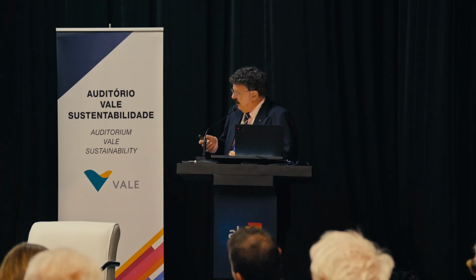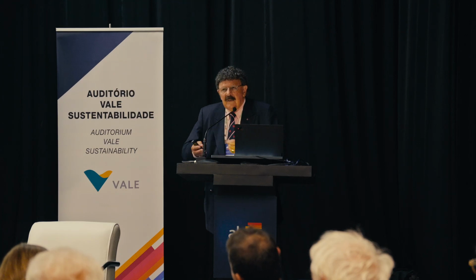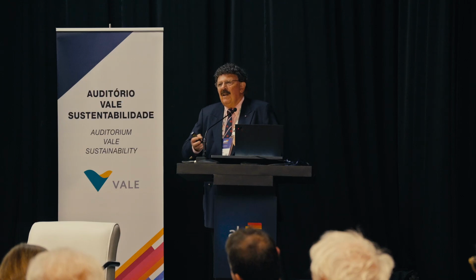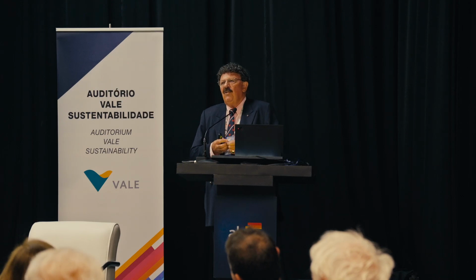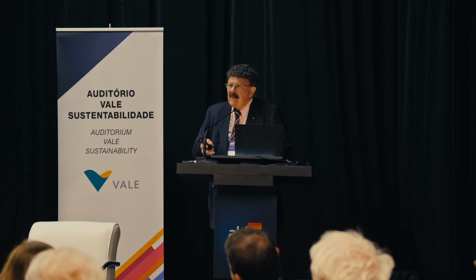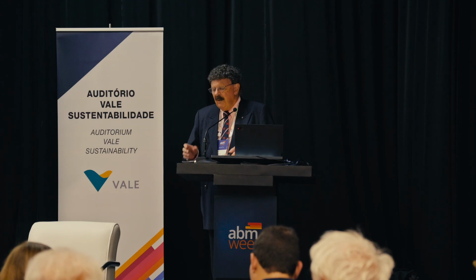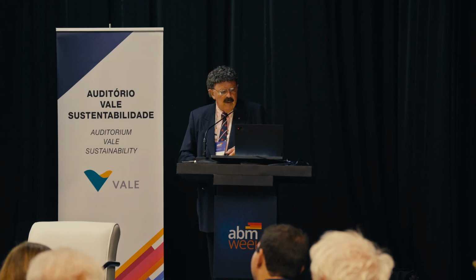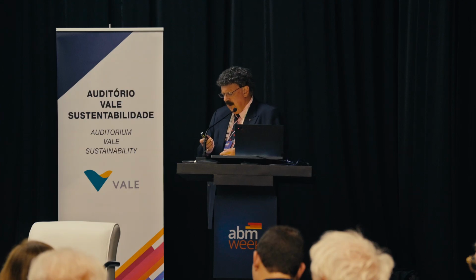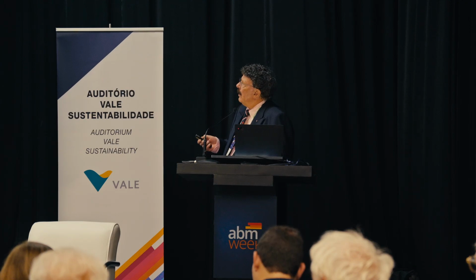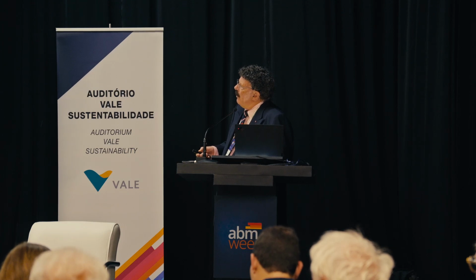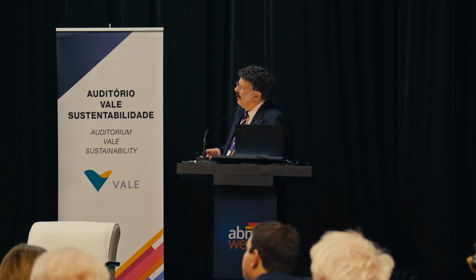And again, we see these sequence of mechanisms of deformation by dislocations, dissociation, formation of another phase, the martensitic phase, and we see amorphous material. We went to even higher strain rates. This was done with laser shock. Again, this was Shiteng Zhao's work. And again, you can see all these mechanisms I've talked about, the very, very planar slip type material. We get twinning formation, and we get the formation of another phase.